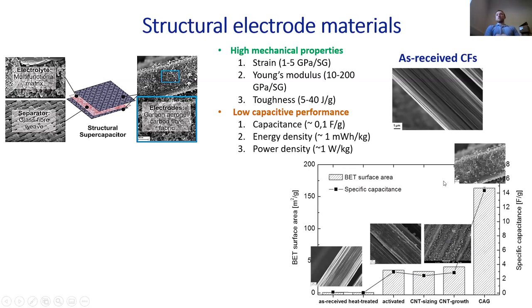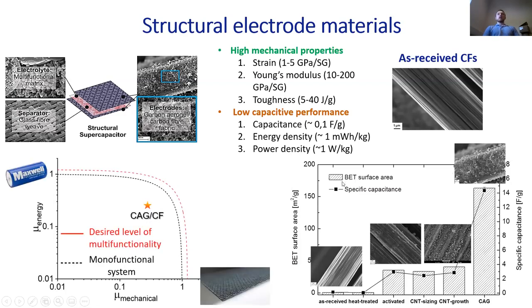But the most successful route was infusion of carbon aerogel precursor, which is basically a 3D interconnected network of carbons forming a small pore size network between carbon fibers and on the surface of carbon fibers. To understand what this means in terms of multifunctionality, it's good to